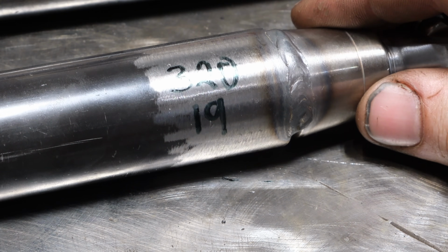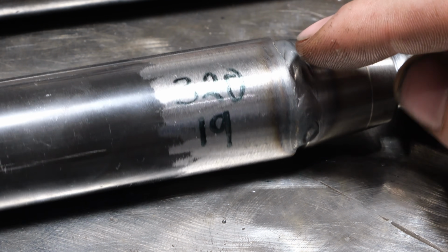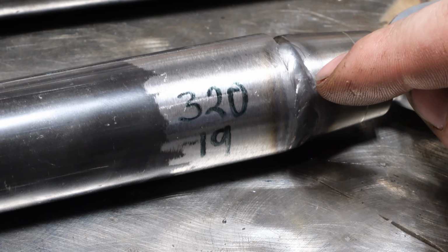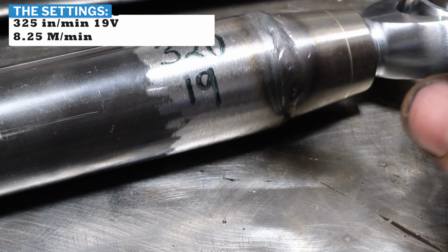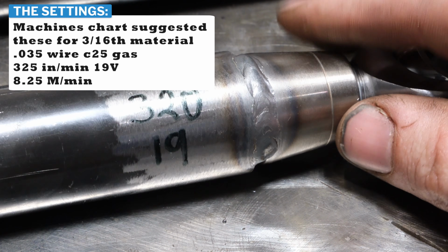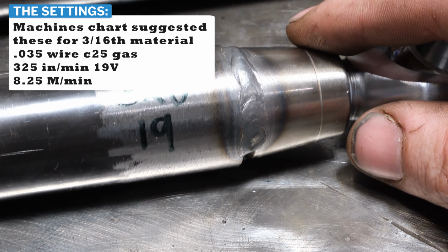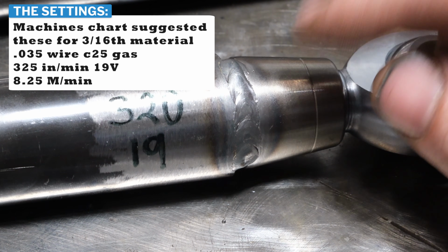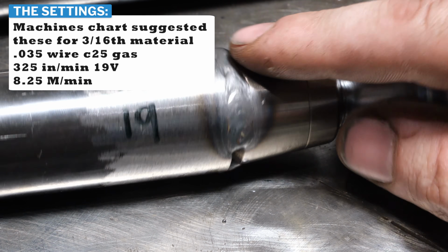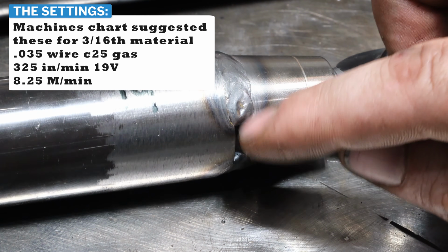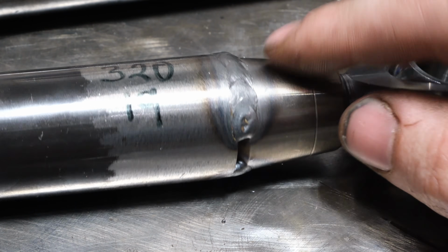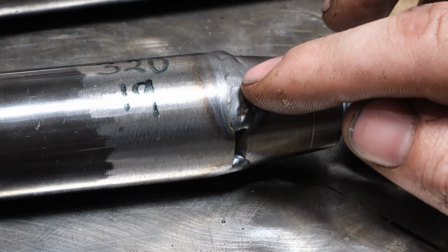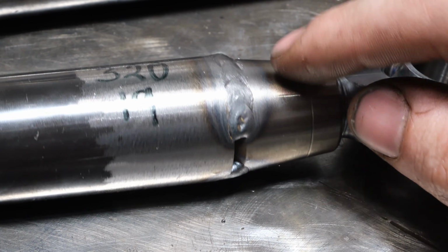So the first MIG weld, which was done at the recommended settings, somewhere in a ballpark of 320 and 19, I'll put up the actual settings right now. That weld went in okay. It's a little difficult welding around the camera, but this half, so right here, very acceptable, very nice profile. It's not concave, it's not super humped up.